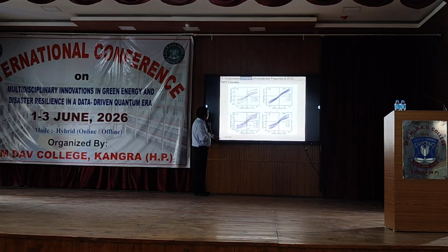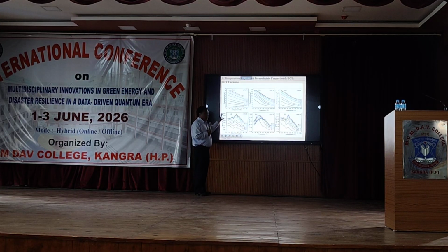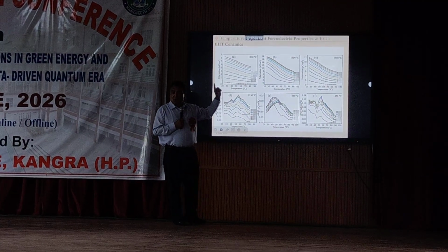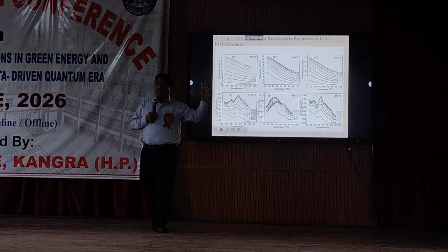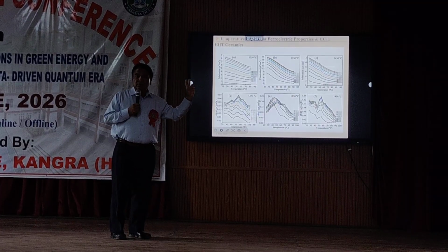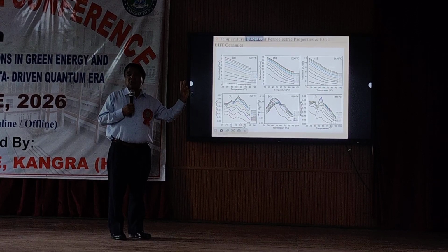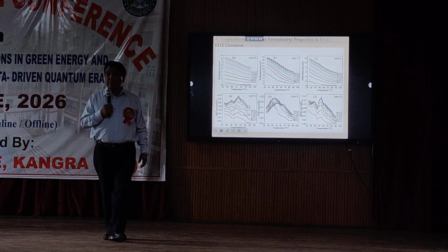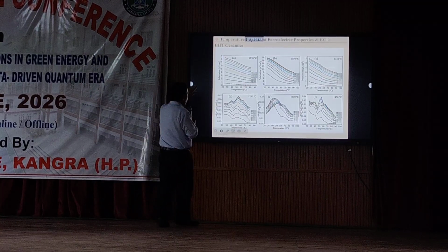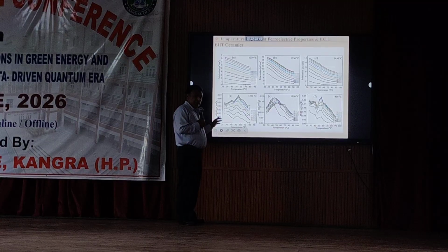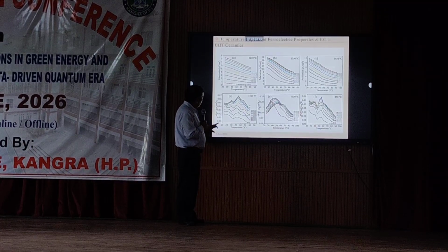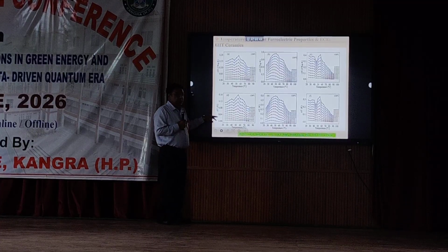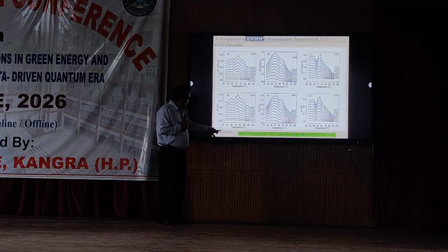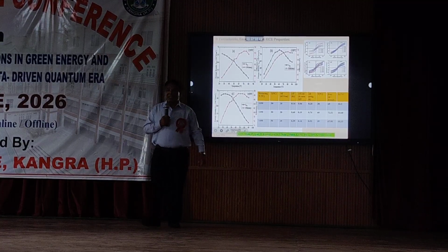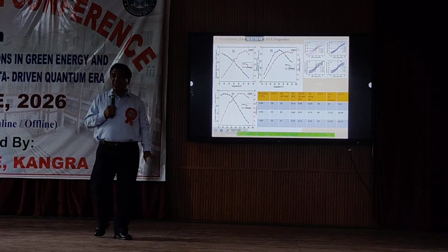Then after doing a lot of calculations, these are the temperature dependent hysteresis loops, from which we have to calculate the dP by dT, because we have seen there are two formulas, one for the electrocaloric effect, delta T, another for the isothermal entropy change, where there is involvement of dP by dT. dP by dT can be calculated from this particular polarization versus temperature, and then from that dP by dT, finally the electrocaloric change in temperature and change in entropy, and then this one is the recoverable energy density, efficiency and total energy.